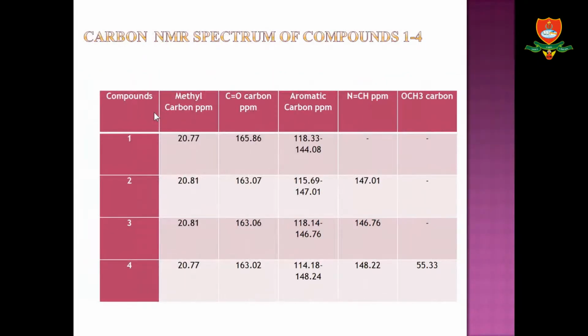This table shows the carbon NMR spectrum of compounds 1 to 4. Here, the methyl carbon is obtained at 20.77 ppm, and the carbonyl carbon at 165.86 ppm. Aromatic carbons range from 118 to 144.08 ppm. And in compound 4, the methoxy carbon is obtained at 55.33 ppm.